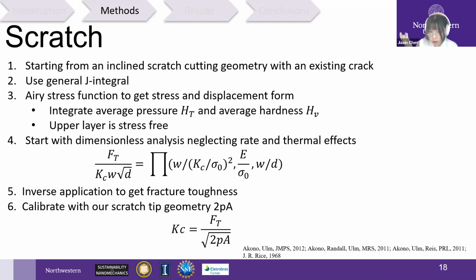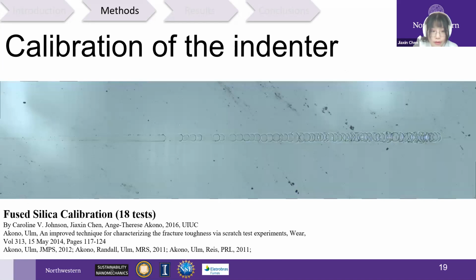More details can be found in the reference paper. For a spherical probe, the shape function is a projected function of the penetration depth. And for a cone probe, it is another function of the penetration depth. Therefore, we calibrate the shape function before testing by carrying out tests on a fused silica reference specimen, as shown